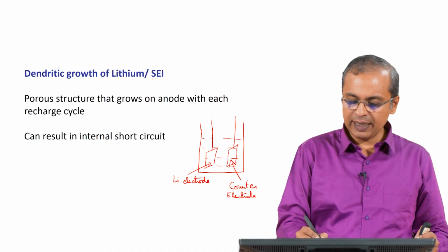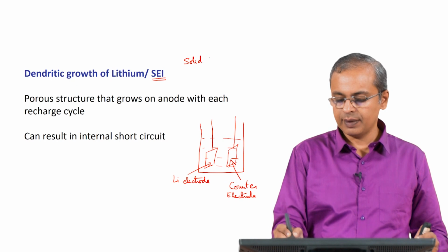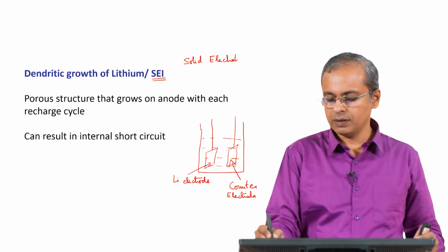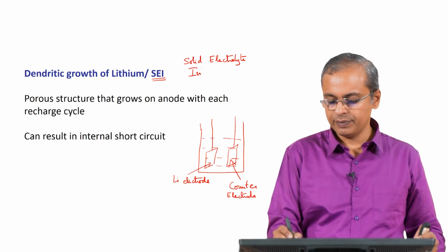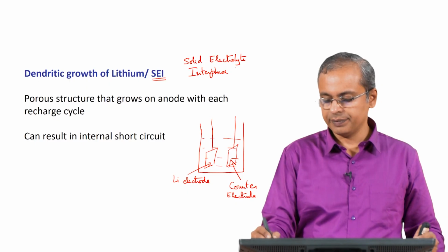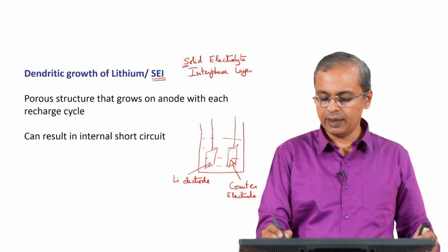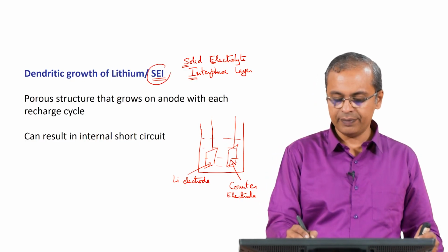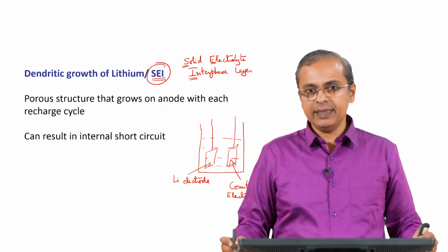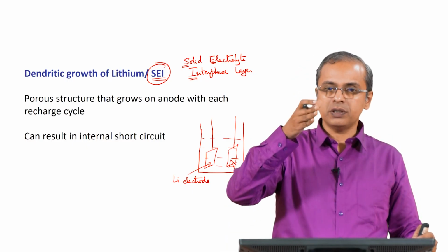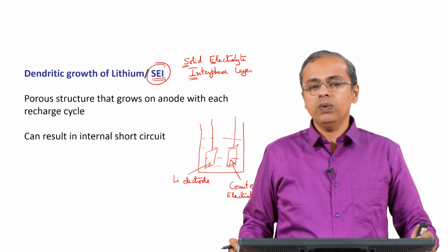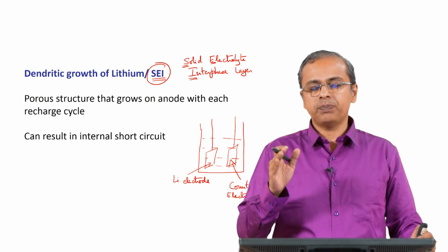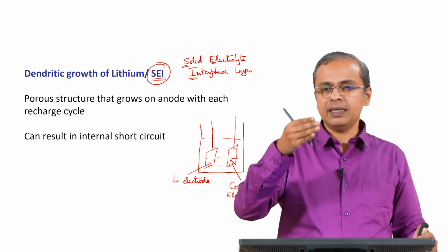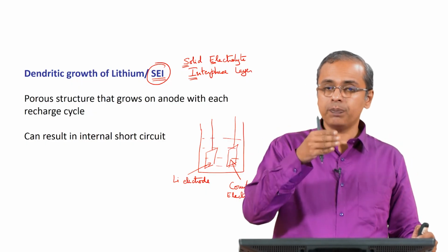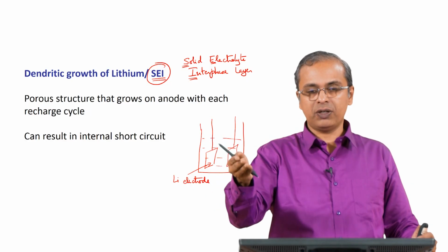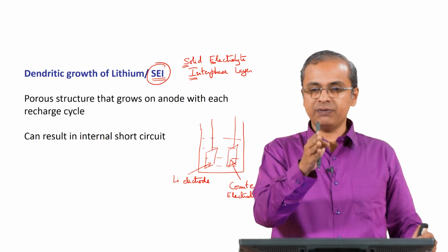This layer is called the SEI layer, or solid electrolyte interphase layer. So, the SEI layer, or the solid electrolyte interphase layer, is the layer that forms because the lithium metal reacts with the electrolyte. Now, this is both a positive and a negative. It is positive in the sense that this layer that forms is a continuous adherent layer and therefore protects lithium from further reaction with the electrolyte. So, it forms on the surface of the electrode and then prevents further reaction with the rest of the electrolyte.